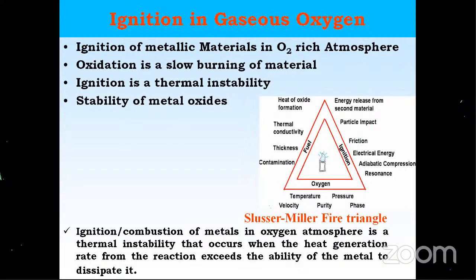Particle impact is what mostly troubles us, because aluminum particles are coming from the tank and can hit the side wall where oxygen is traveling. Friction can generate heat and increase the temperature. If it crosses the ignition temperature, it can cause ignition under oxygen conditions. Electrical energy, adiabatic compression, and gases can all cause ignition. Oxidation is a slow burning of material, whereas ignition is thermal instability, where catastrophic failure can happen.